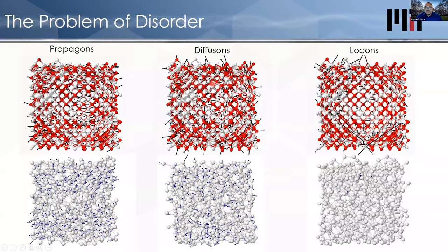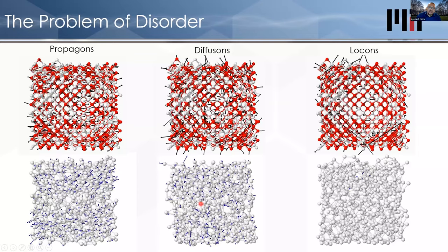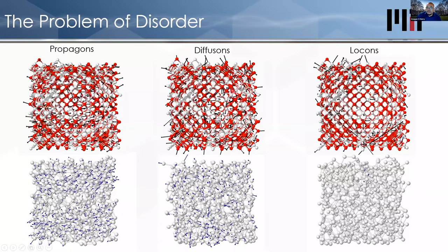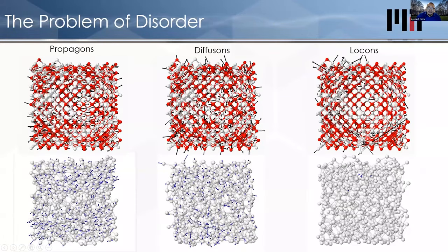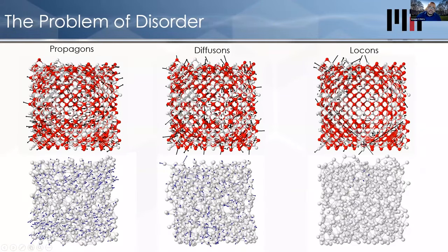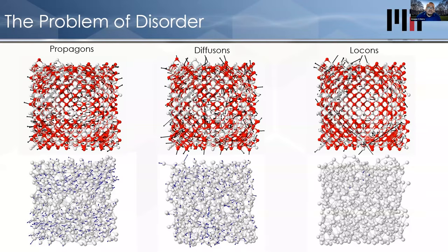Now the majority of the modes look like this, look like random vectors pointing in all kinds of different directions. This is an alloy. This is an amorphous material. The same classifications of modes show up in alloys, even though they have crystalline structure but disordered composition, or disordered structure and uniform composition. In either case, you get these new classifications of modes that show up called diffusons and even locons, where you have localized vibrations where only a small group of atoms are participating in that mode. So this is a major departure from the normal physical picture we had before.